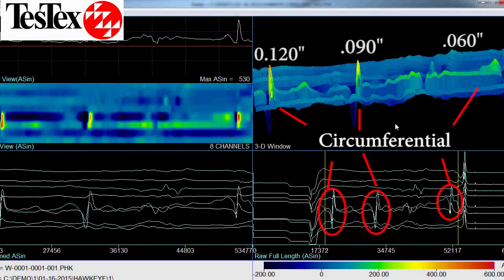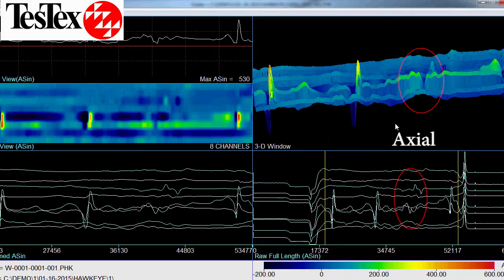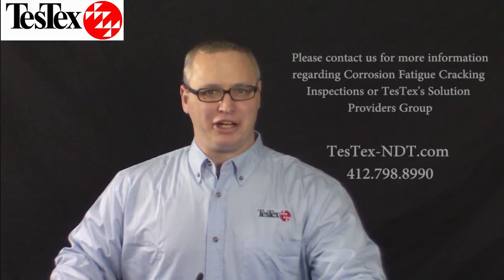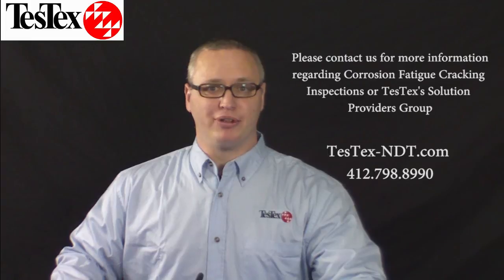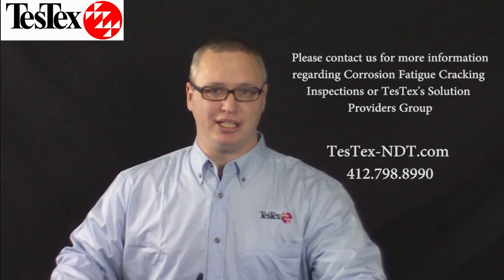When we use the analysis software, we can see a 3D waveform that shows circumferential cracks with the depths of 60 mils, 90 mils, and 120 mils. We can also see an indication of axial cracking, but we would have to use a rotating probe to size it. Here at TesTex, we are constantly improving our non-destructive testing capabilities.